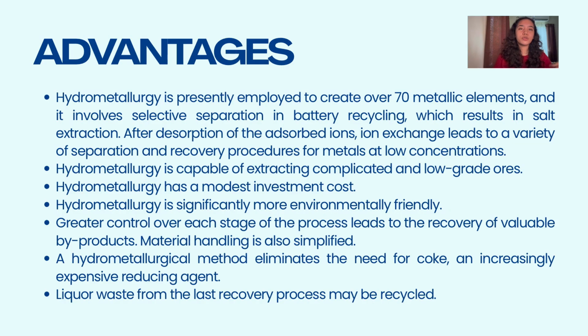allows for fine tuning of parameters like pH, temperature, and reagent concentration, giving engineers precise control over which elements are dissolved and when. This allows sequential extraction, enabling the recovery of secondary metals such as molybdenum and rhenium from copper concentrates, or nickel and cobalt together. These byproducts, which might be lost to slag in smelting, add significant economic value.